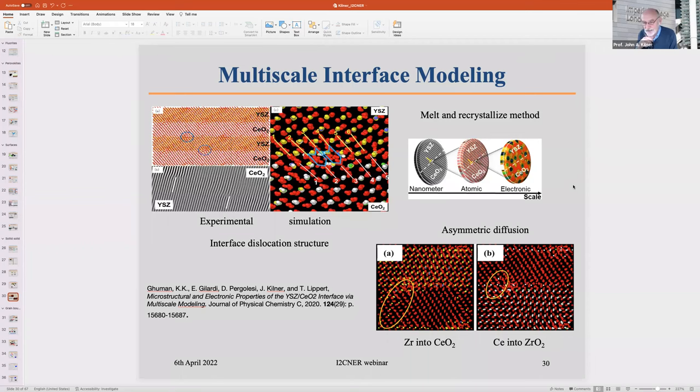People have looked at this in the past, and I really have to go back to the literature, but my memory is that it wasn't found to be too important for the oxygen conductors. I've worked on lithium conduction in the perovskite lithium lanthanum titanate, and I think interaction between the two sublattices is quite important. Correlation effects between the moving lithium ions are important as well, which is not so important in these vacancy diffusers, but might be important in the interstitial diffusers that Tatsumi Shihara was talking about. I see. Thanks for your answers.